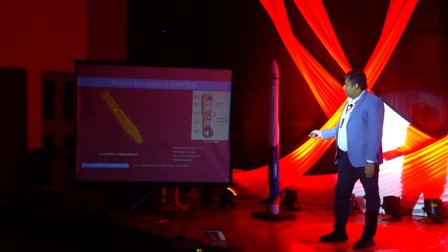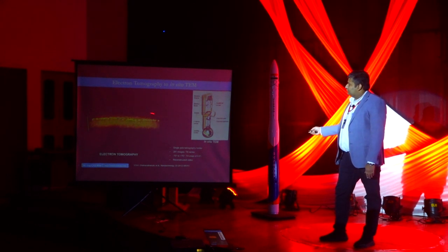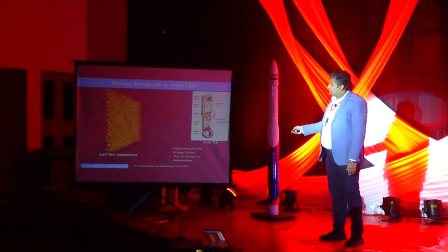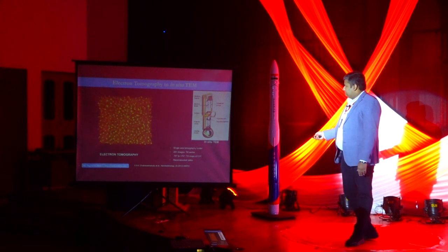So I had to go for an advanced method of electron microscopy. Learning this method with the group of Professor Kienle, it was a wonder. So I tried to study these things using electron tomography, a three-dimensional imaging technique inside electron microscopes, where we were able to see the particle size distribution and come to various conclusions or hypotheses, where we were able to see larger particles on the top surface, smaller particles within the matrix.